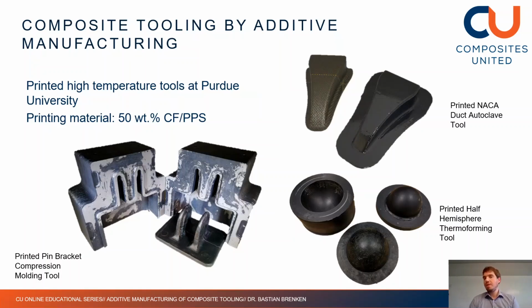Of course, these tools then don't last forever. It's still a thermoplastic material. This material still creeps when you heat it up and apply a big pressure. So just to give you an idea, an example, the printed compression molding tool there lasted for about 10 cycles and then it broke. But for prototyping or for very small number series production, or for a tool during the tool development phase, so that's still a huge potential that you can see there in printing tools.